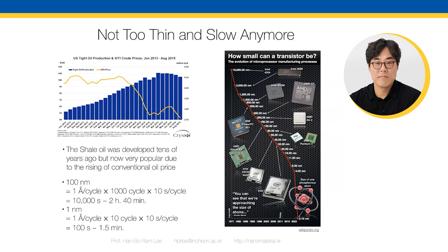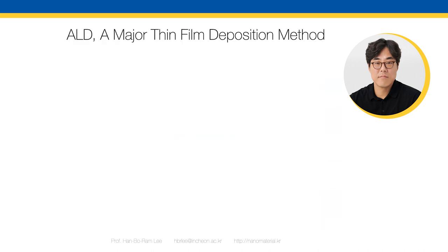Here's a good analogy: the USA already researched how to extract oil from sand and rocks — shale gas. Almost 20 to 30 years ago, they finished all the research, but the problem was cost — at that time, oil prices weren't very expensive so they couldn't use the new technology. But now, with higher oil prices, they can extract a lot of oil from sand and rocks using shale gas technology. The same situation happened in silicon chips. Silicon device size decreased a lot. Twenty years ago, you needed to deposit 100 nanometers — with ALD that took two hours and 40 minutes. But now we only need to deposit one nanometer, which takes about one minute and 30 seconds. So ALD is not slow anymore, and all deposition technology is moving toward ALD.